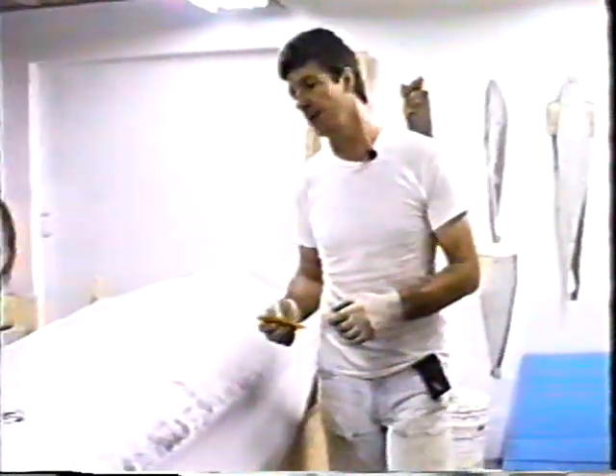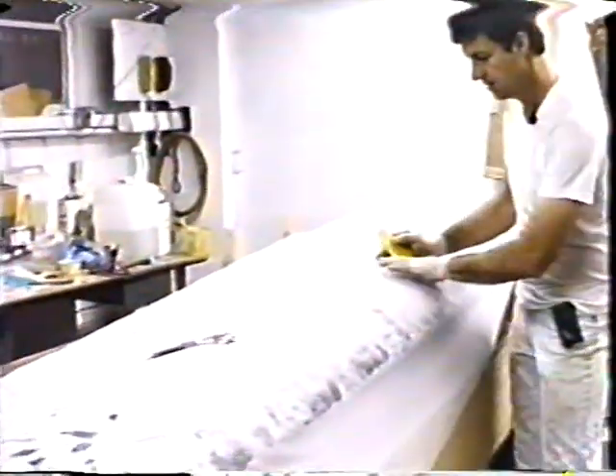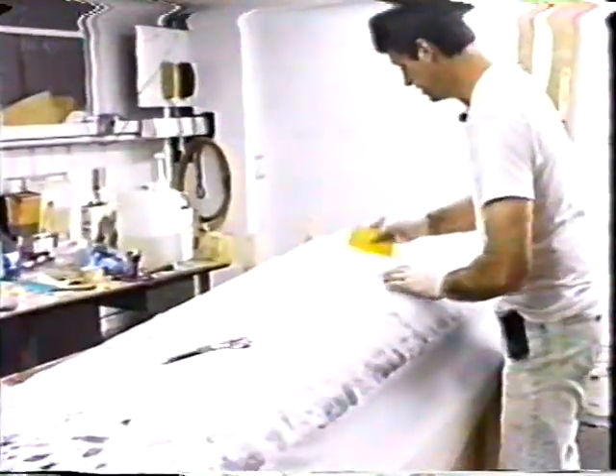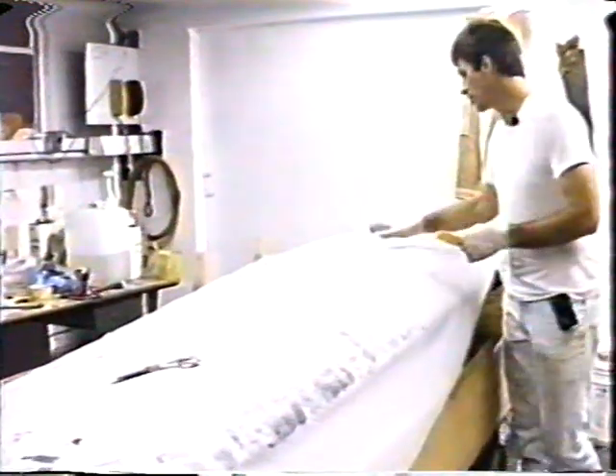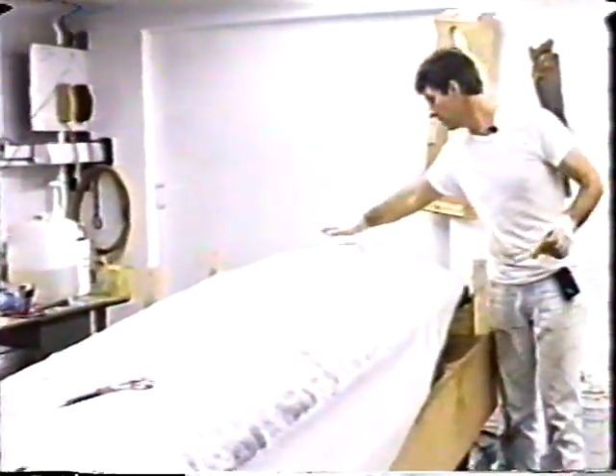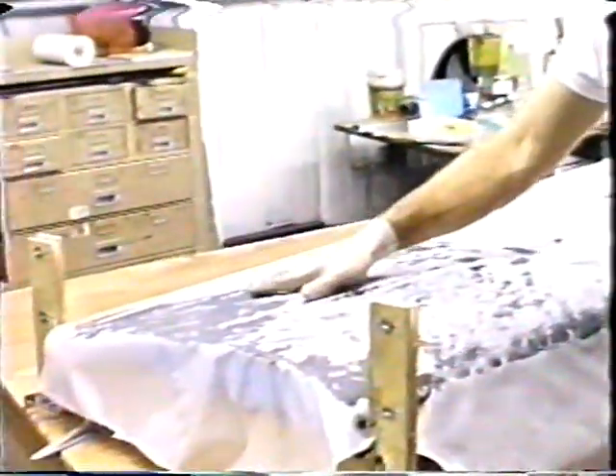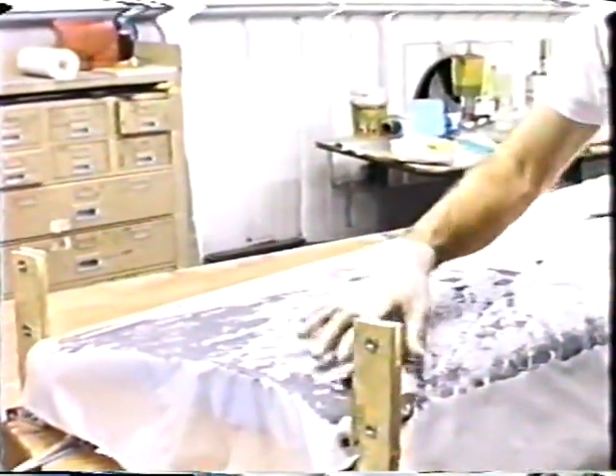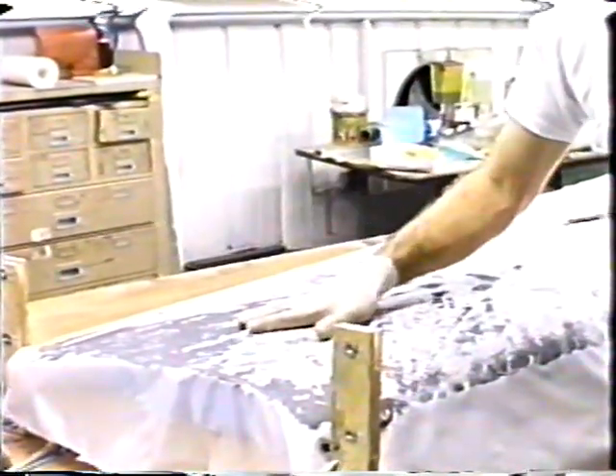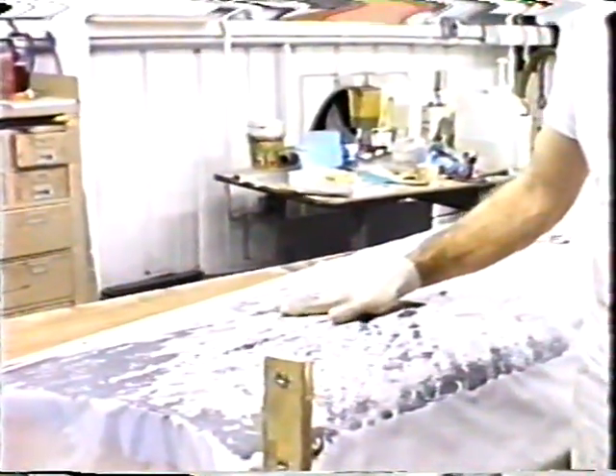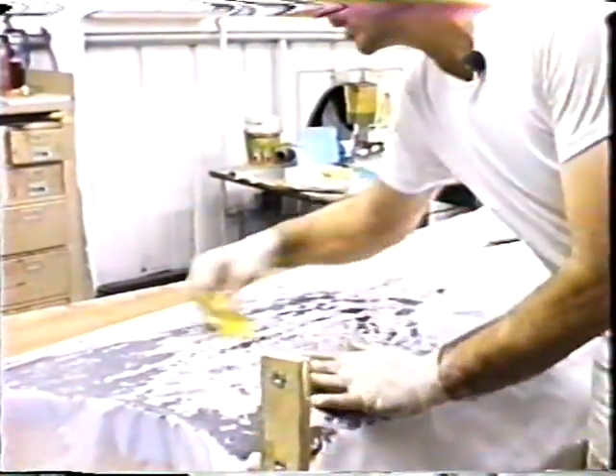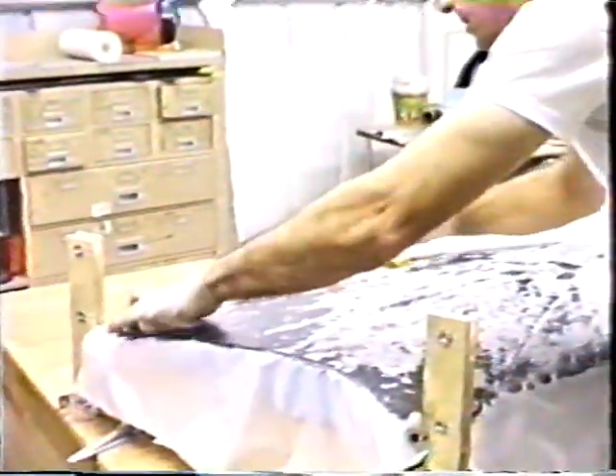Now that we've got all the plies on, leading edges are wet, and the added unidirectional reinforcement tapes are in these areas, here and here, and the 2 plies of carbon fiber unidirectional. First one at a 45 degrees to the spar, second one 90 degrees to the first one. So we have the equivalent of a ply of bid of carbon fiber out here. Wet this out. Tuck it into the corners.